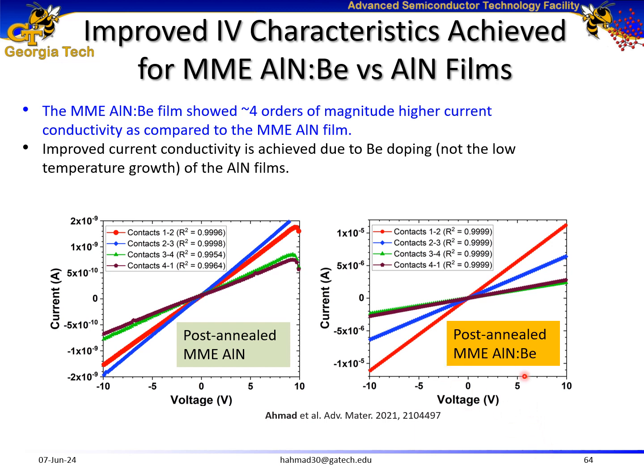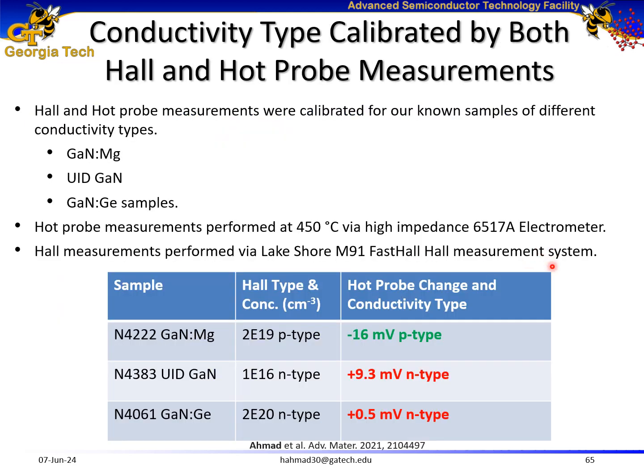Furthermore, from comparison of a beryllium-doped aluminum nitride versus annealed undoped aluminum nitride film, we see an improvement of approximately 4 orders of magnitude. So it's actually the beryllium doping which improves the conductivity of these samples. Later, I wanted to validate the conductivity type of these samples with both Hall measurements and also hot probe measurements.